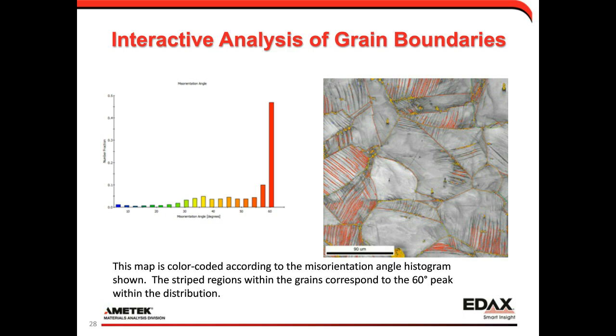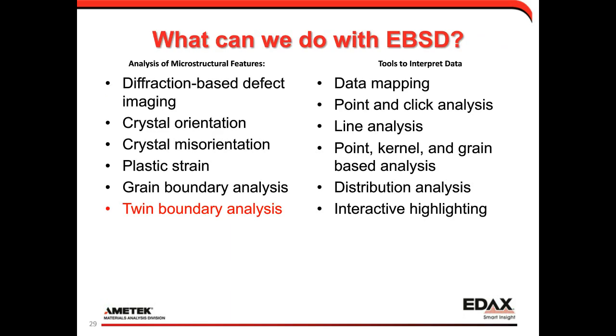And what we see is there's a lot of red boundaries now in that microstructure, and those red boundaries correspond to those striped boundaries within the grain. And so that leads to the idea of, those striped parallel boundaries, of course, make us think of twin boundaries. So we can actually do some twin boundary analysis with EBSD and OIM.